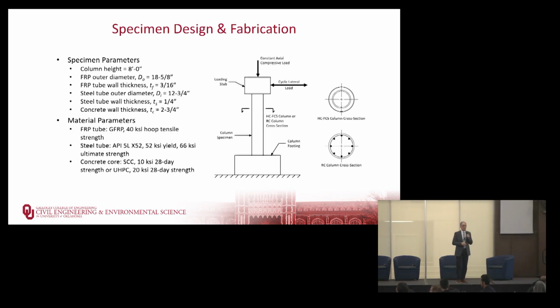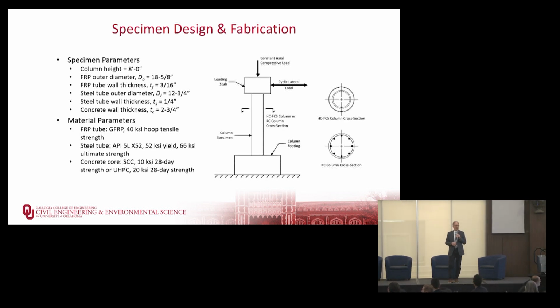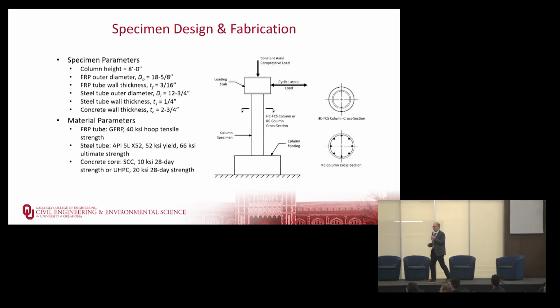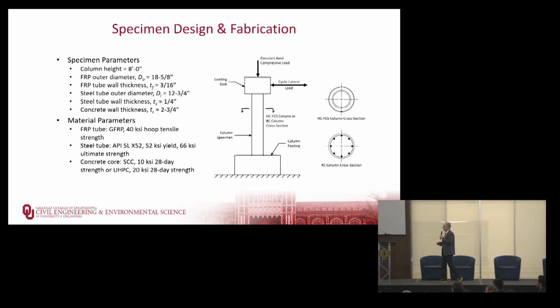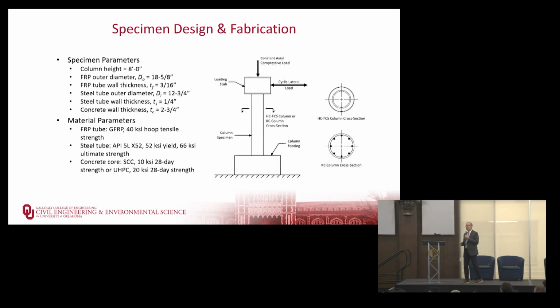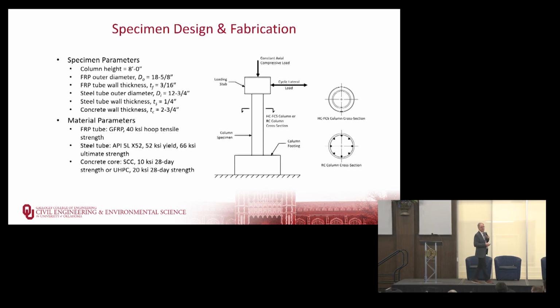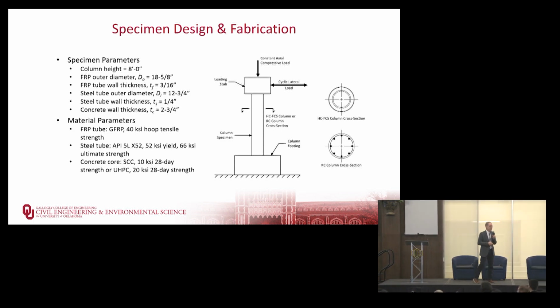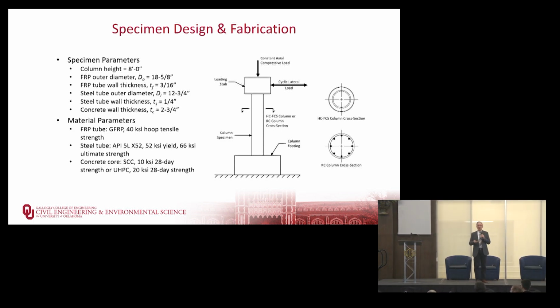And we used our UHPC mix we developed at the University of Oklahoma with a target strength of 20 KSI. Technically, UHPC is 21.7, but we figured doubling the strength would work well. And both of those concretes flow very, very well. Tyler showed you how essentially UHPC is also a mortar, right? It's just sand and cement and water and high range water reducer. So it's a mortar with fibers in it.